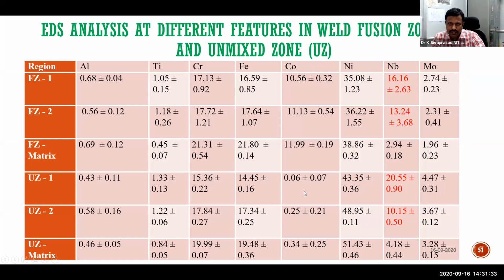Then EDS analysis with different features in a weld fusion zone. Here, niobium concentration was observed in fusion zone 1, fusion zone 2, and unmixed zone 1 and unmixed zone 2. So in both the fusion zone and unmixed zone locations, the niobium is becoming rich. Niobium rich is advantageous, but unfortunately a small amount of carbon which has arisen from the Inconel 718 started forming niobium carbides. Discrete niobium carbides are favorable. Continuous niobium carbides, a network of continuously found niobium carbides, are detrimental.